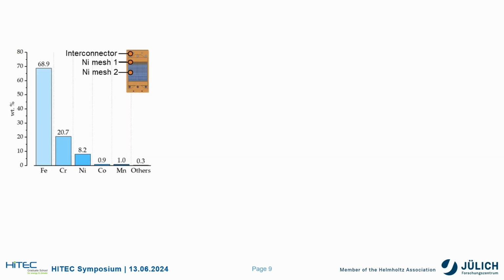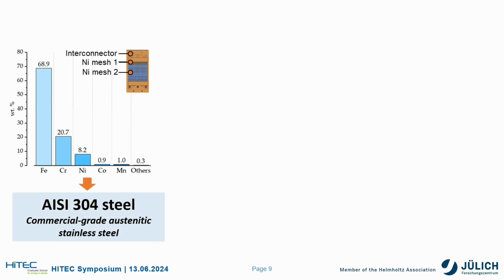So through our characterization, we concluded that the sample is primarily composed of iron, chromium, and nickel, with less than 3% of trace elements such as cobalt and manganese. This composition closely resembles an AISI 304 steel, which is a commercial-grade austenitic stainless steel and belongs to the most common and versatile type of steel families.